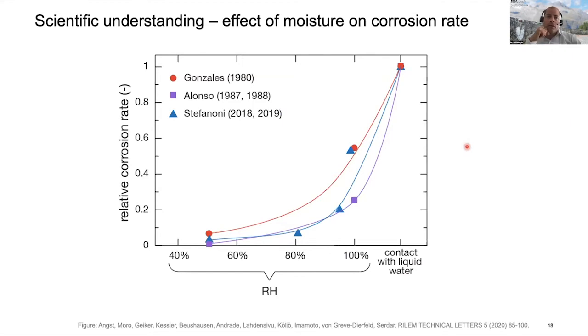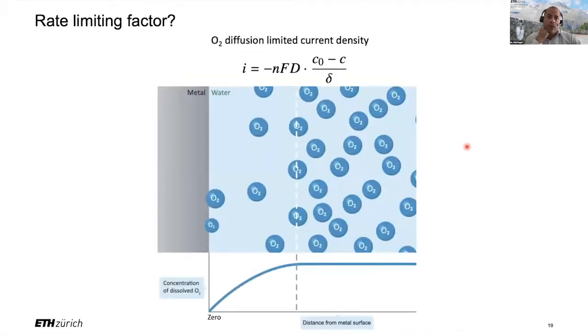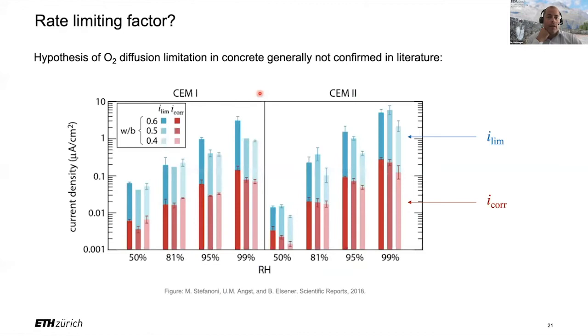So what controls the corrosion rate of steel in concrete? It's really the question, what is the rate limiting step here? And again, if we rely back on an understanding of steel corrosion in electrolytes, then often one rate limiting factor is known to be oxygen diffusion towards the metal surface, which is then represented by the oxygen diffusion limited current density. But when we try to apply this concept to steel corrosion in concrete, we actually find that the oxygen diffusion limited current density is approximately 1 order of magnitude higher than the instantaneous corrosion rate.